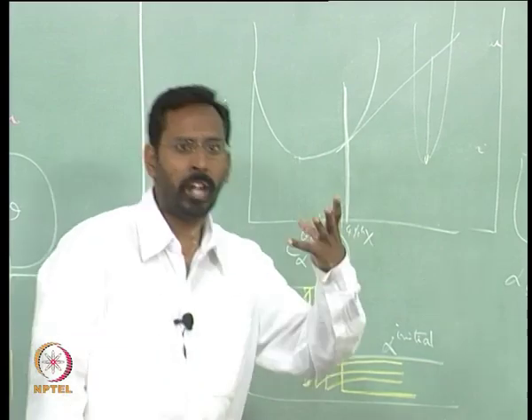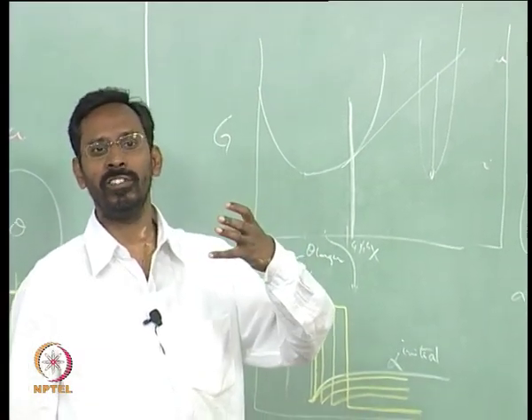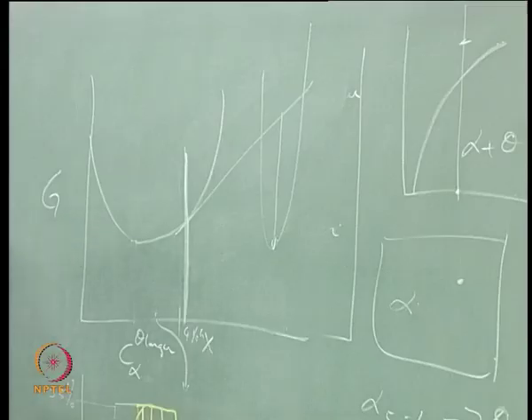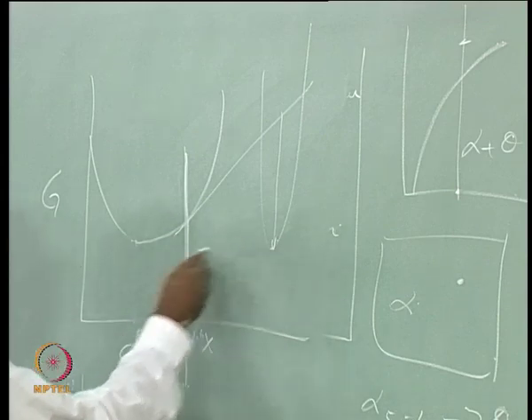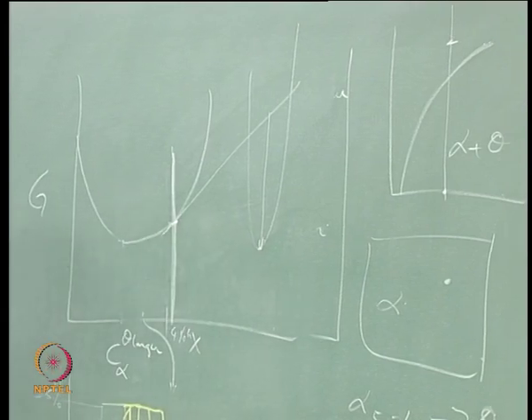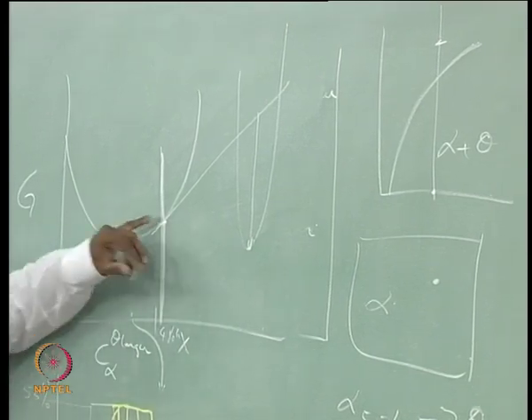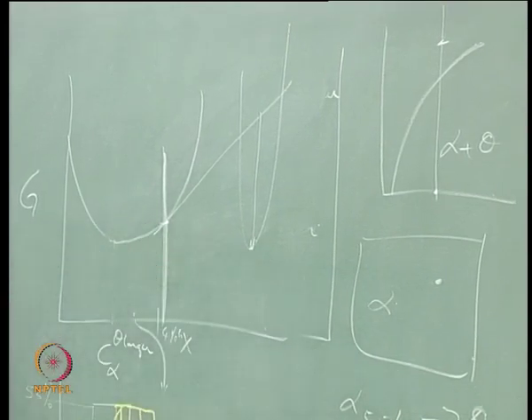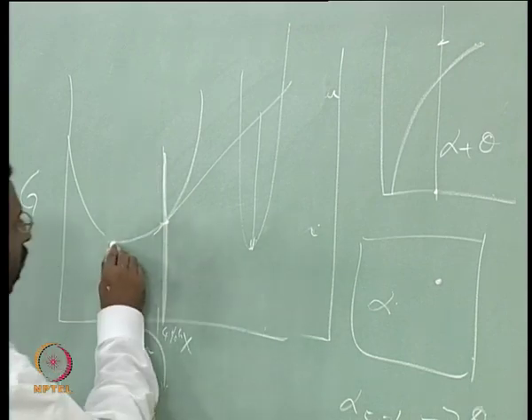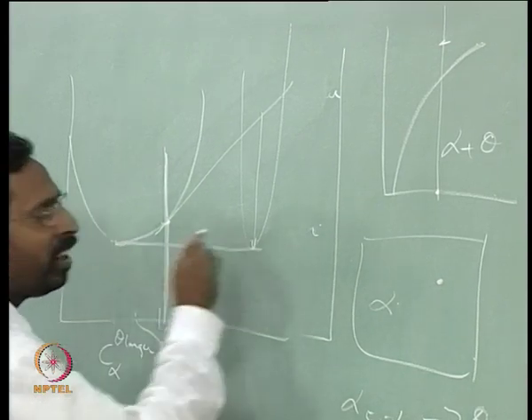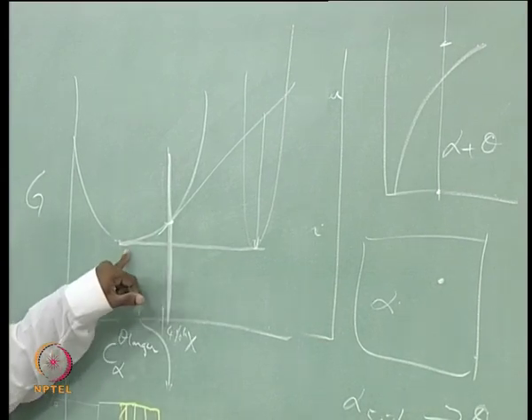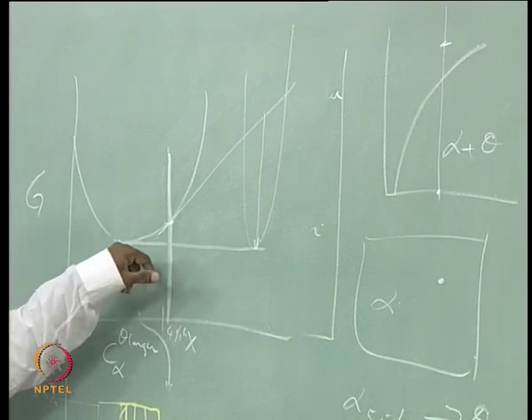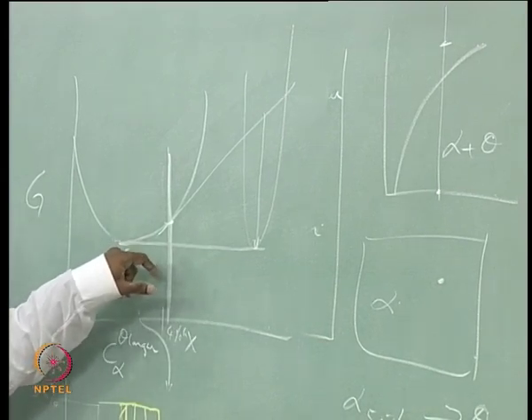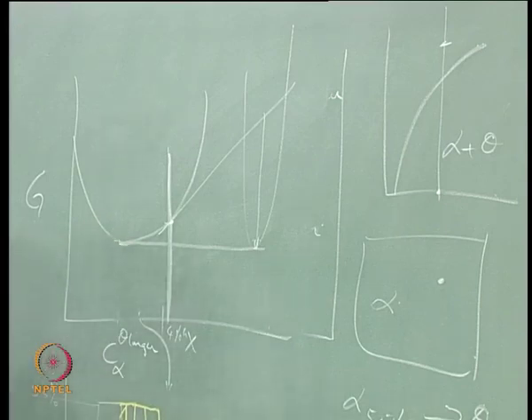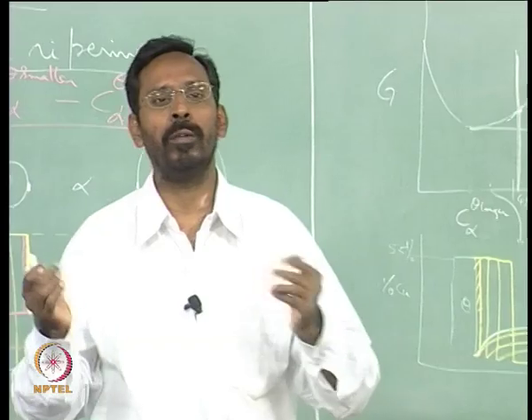The moment theta nucleates inside the alpha, either at a grain boundary or wherever it is, this theta cannot be in equilibrium with this alpha. It is impossible to have a common tangent between the two. So, this theta will find some composition of alpha with which it can be in equilibrium, and as a result the alpha adjacent to that theta will have a different composition.